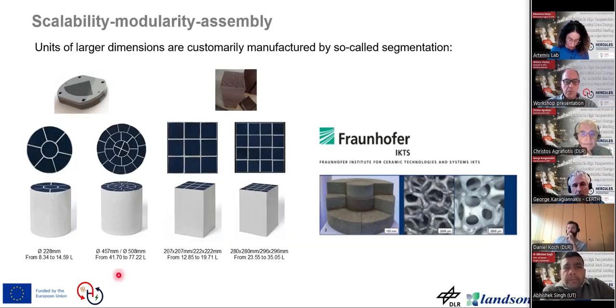Next slide, please. This shows how we can assemble big units either from honeycombs or from foams. So it's not necessary, and it's also very dangerous in case of cracks, to have a single monolithic body of the dimensions that we want. Industries that are doing this stuff produce so-called segmented pore structures. One can extrude or make out of foams smaller pieces that are easier to manufacture, and they also are replaceable, and this shows the concept of modularity.